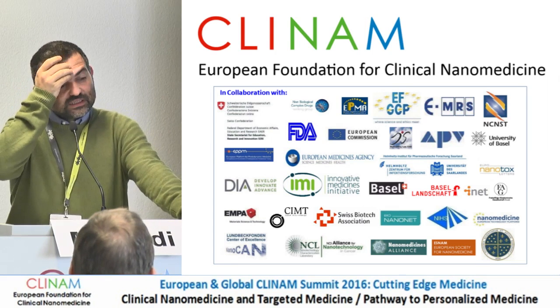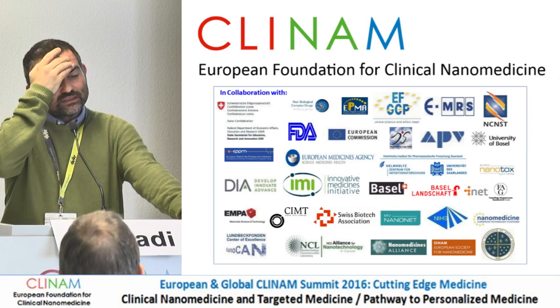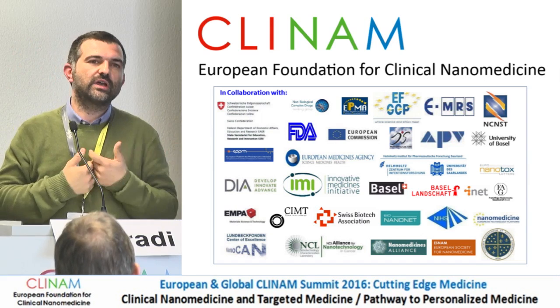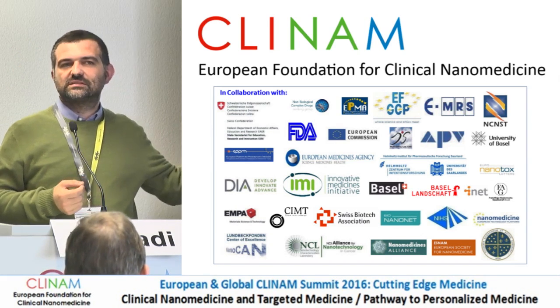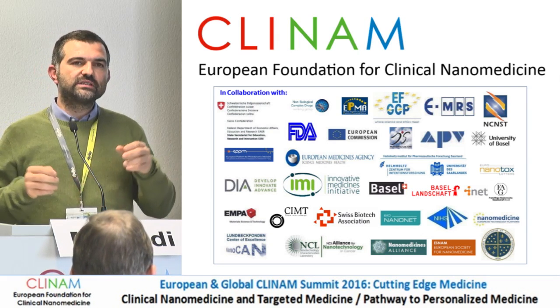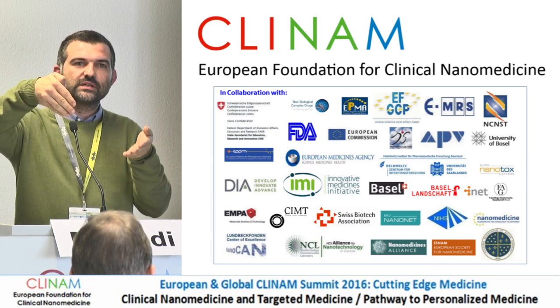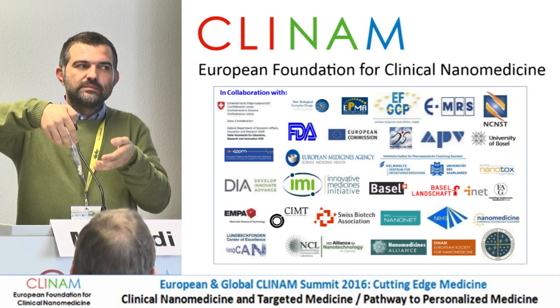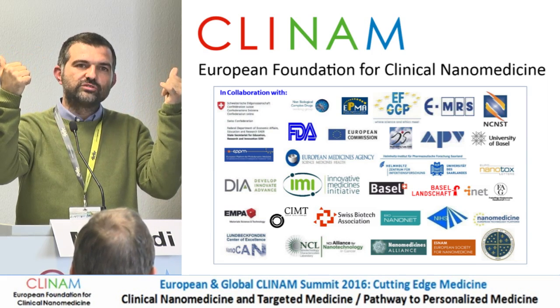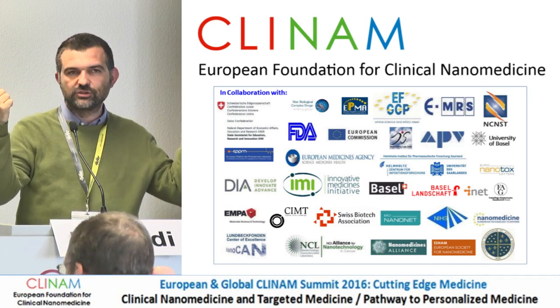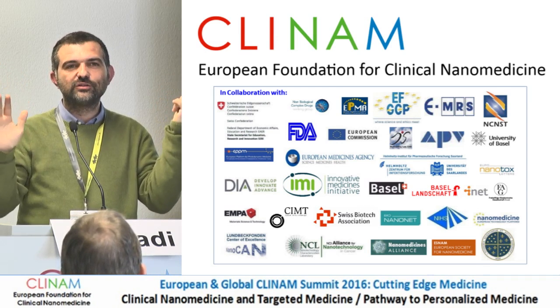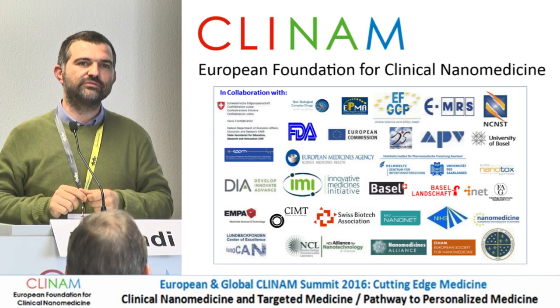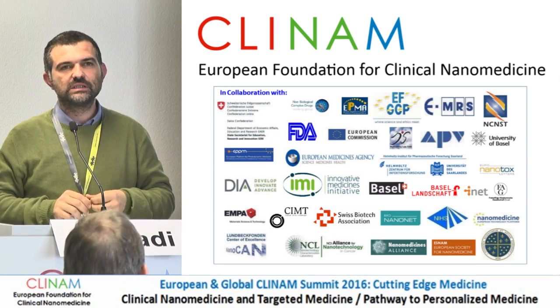Regarding steric hindrance — I was actually more worried about the non-covalent binding approach, which was the initial idea. A system releasing doxorubicin non-covalently would be easier and preferable. In the current covalent system, the alkyl chains of the cross-linker are likely pushed to the inside of the nanoparticle, so the carboxylic groups and doxorubicin are completely exposed on the surface — also supported by zeta potential measurements. The advantage is that the surrounding dextran provides water solubility to the system.